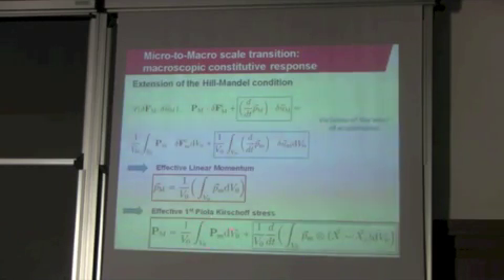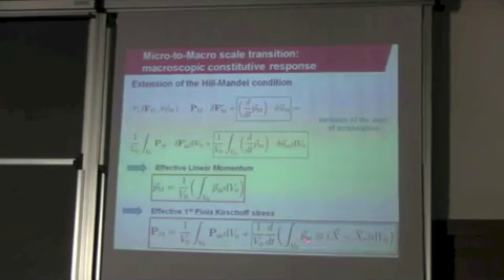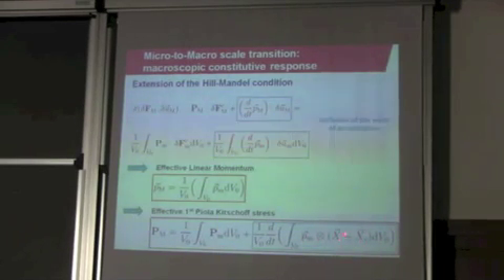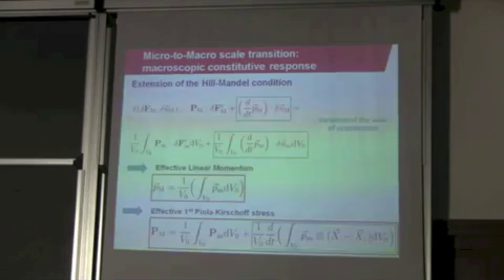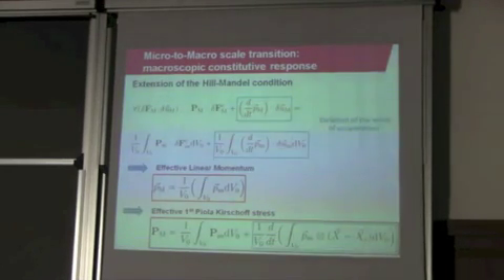So we again have the classical term, which is the volume average of the microscopic stress, plus this term that includes the momentum, and this term is in fact related to the RVE size. So xc is the center of the RVE, and this is then the position of the point with respect to the center. And this is then the dyadic product of these two. Also interesting to note here is that this term will introduce the size dependence in the whole simulation, so that the result of the local resonance frequencies will depend on the size of the microstructure, as is of course the case in these materials.